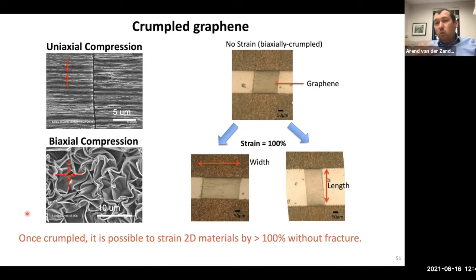So you might be asking, well, why the heck are we crumpling this material up? And the reason is, if we want to make stretchable electronics, we need a stretchable material. If you take a flat piece of paper and we stretch it, even by a couple of percent, it's going to tear. If we take something and first crumple it up, now, without breaking it, we can stretch and unstretch it by a few hundred percent, and it's not breaking. So this gives us a way of making stretchable systems.